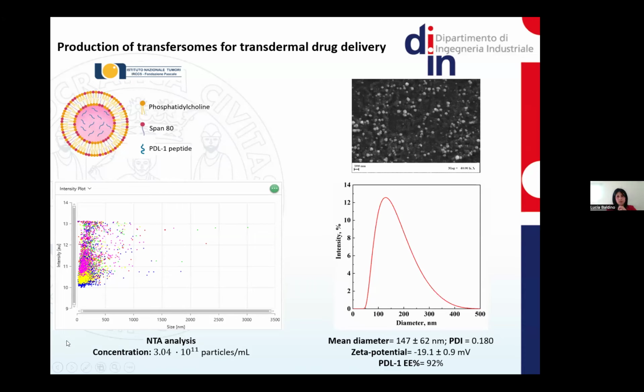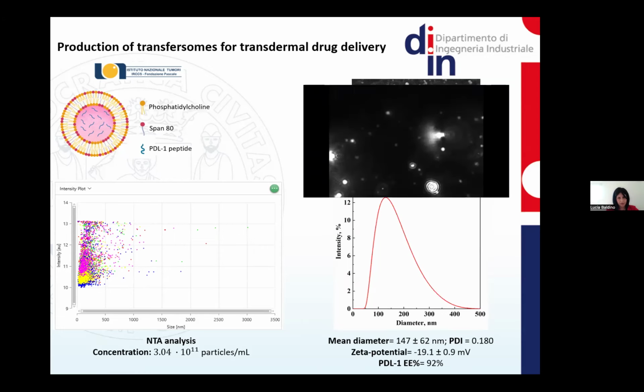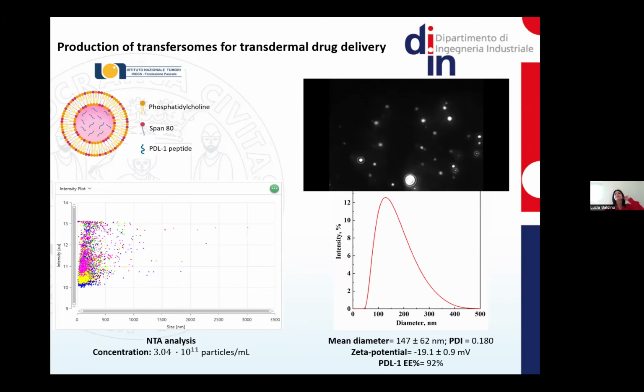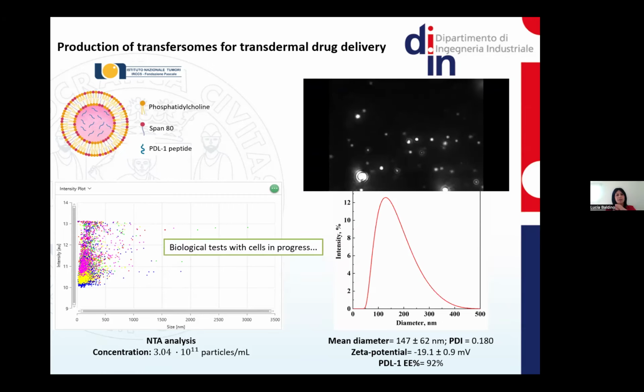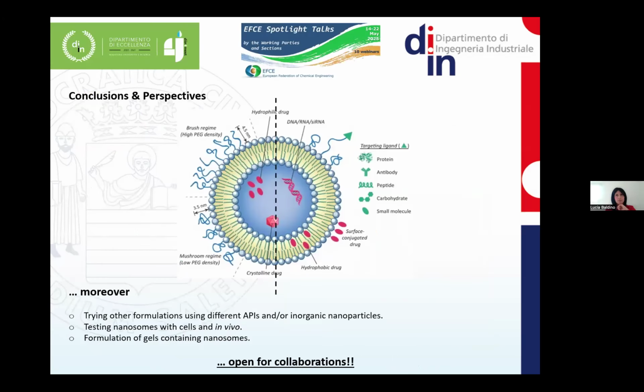By using NanoSight, and so by performing nanoparticle tracking analysis, we demonstrated that most of the vesicles were in the dimensional range between 0 and 200 nanometers, in line with SEM and DLS analysis, and particle concentration reached 10 to the 11th particles per ml. Here we can see from this dynamic frame the regular shape of the produced transfersomes. And currently, biological tests with cells are in progress.